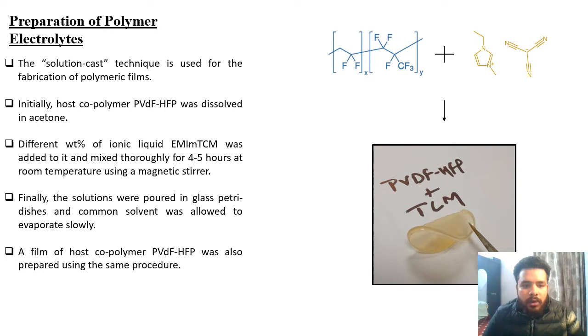After adding different amounts of EMIM-TCM, I have mixed it on a magnetic stirrer for 4 to 5 hours. When it is completely dissolved, I have poured the solutions into glass petri dishes and allowed the solvent to evaporate slowly. I have also made a pure PVDF-HFP film by using the same method. The films I have prepared are characterized by some characterization techniques.